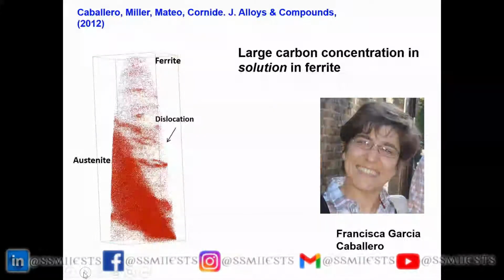Now, why would it remain there, even though we are holding at the transformation temperature for 10 days? Why does it remain there? Recently, there was a paper published in one of the Nature journals saying it must be because the carbon is trapped at vacancies. But you can do a very simple calculation to show that the fraction of carbon atoms that are trapped at vacancies will be incredibly small. So there has to be another reason why the carbon remains inside the ferrite, even though you give it every opportunity